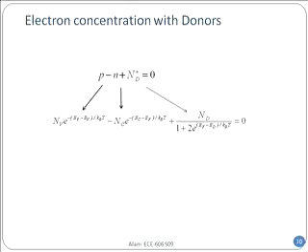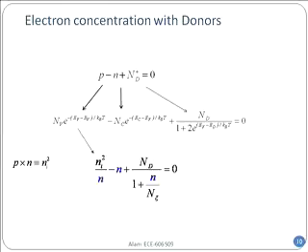Look at this. That's the full expression. I don't write Na minus because it is an N-type material, right? I don't have any acceptor. Now, do you agree with this statement? I have written the previous one in the expression below, and it has several tricks that you should remember. The first one is this. You see the first term on the left-hand side that goes with the valence band and the number of holes, that expression, P multiplied by N on the left-hand side equal to Ni squared.